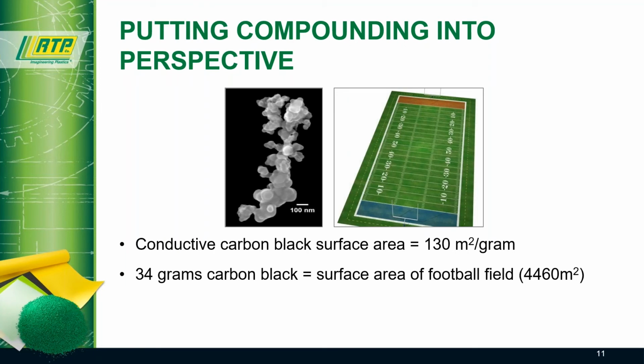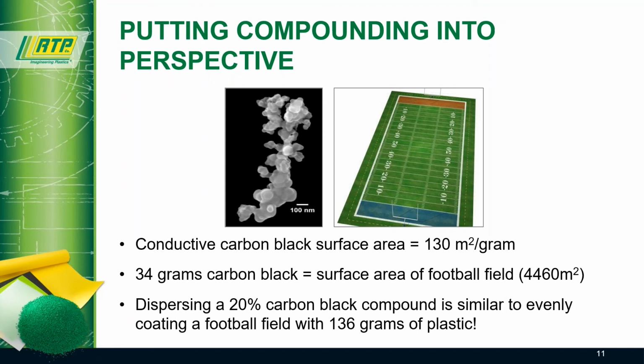On the flip side, a football field or soccer field has a surface area of 4,460 square meters. So that is equal to about 34 grams of carbon black. In a conductive compound, for instance, there would be 20% carbon black, and the objective of the compounding process would be to wet out the surface area. Wetting out that amount of surface area is similar to coating the entire surface area of the soccer field with only 136 grams of plastic. It's a lot of work.